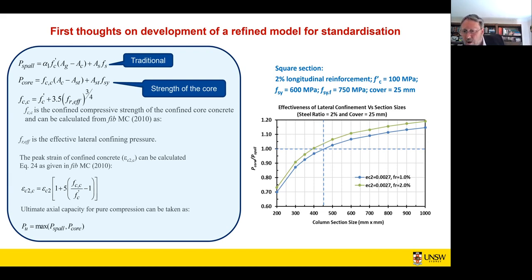And we look over here on the right and note that we're required to use 1% confinement reinforcement, irrespective, with high strength concrete columns. And we see here anything that's less than about 450 millimeters square, we don't get any benefit. So in our lab concrete, we don't see the benefit there because our columns are not of sufficient size. But if our column was a metre square in a large building, we actually get a 15% benefit. Then if we increase the core confinement from 1% to 2%, that goes up to 20%. How do we get empirical evidence of this? And that's the challenge, because these types of tests can be done, but they are not cheap.